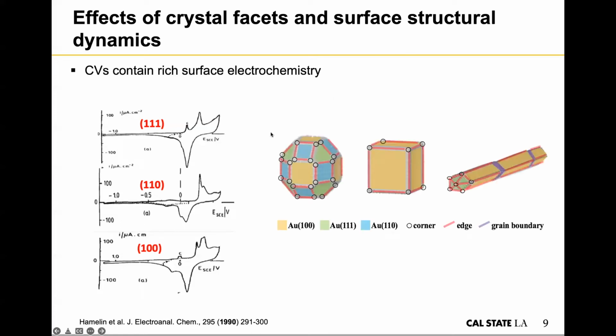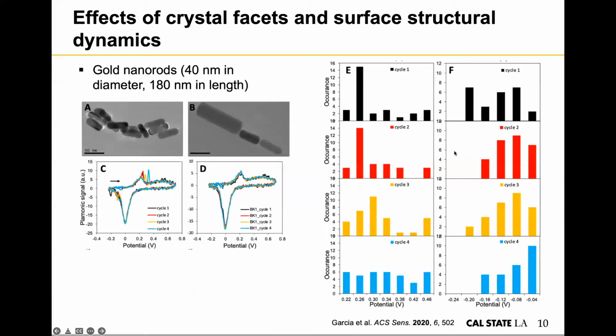And we know that different particles are composed of different facets. So in the next work, we tried different combinations: nanospheres, nanocubes and nanorods, which can have different ratios of 100, 110, or 111 surface facets. I'm not showing you all the results here because I don't think it's fully conclusive. It's still a topic that needs further investigation, but I'm showing you one example here we did with gold nanorods.